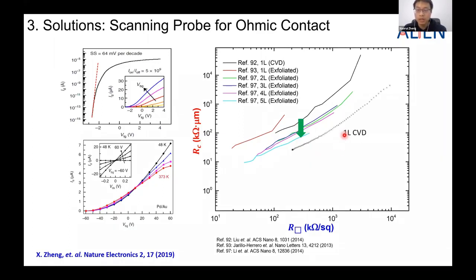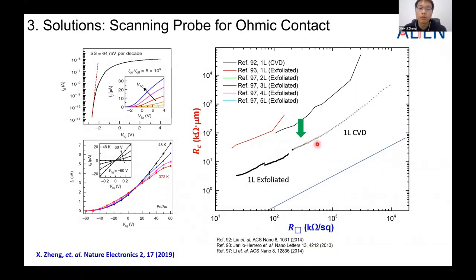So this is the result for one layer CVD sample. You can see clearly we actually bring down the contact resistance at the same sheet resistance of the material, and we further reduce the contact resistance by using a more conductive material, the exfoliated MoS2 monolayer. And as you can see, we bring down the trend around 1 order of magnitude. And in future, this is the requirement for industrial application. We still have some room to further improve the quality of the contacts.